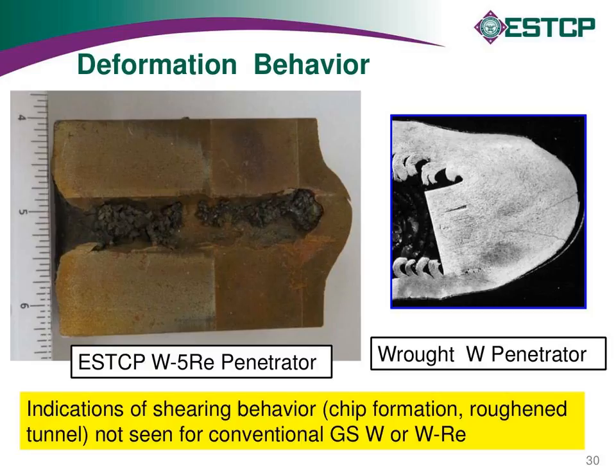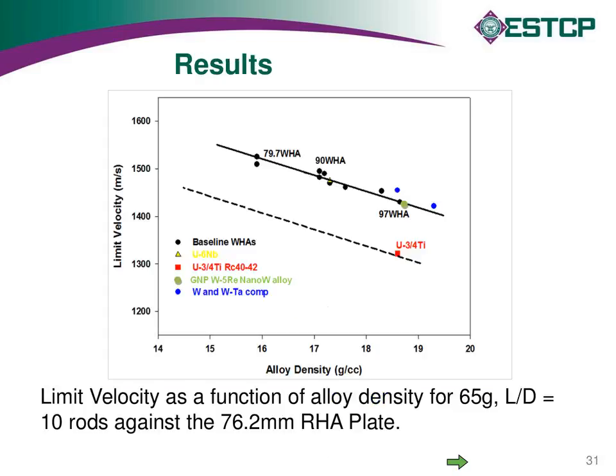Just to show where we are, the next plot, the data point. If I had to assign a limit velocity to that one shot, it was very close to getting through the target. So we were right on the edge. So it's basically on the conventional tungsten heavy alloy line. Like I say, if it had been a pure tungsten type material, it would have been above the line. So we were seeing some improvement, but not a very dramatic improvement, and well short of the gap you get with the U3/4 Ti alloy.